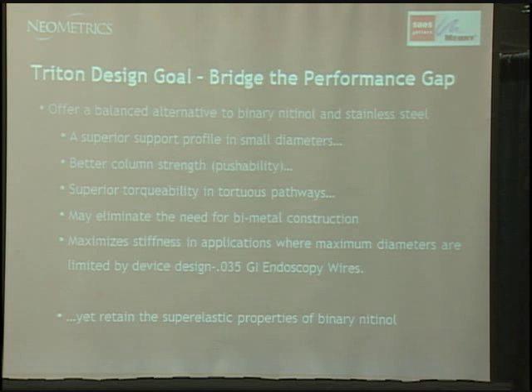So the solution to this performance gap between the two different materials is what we're calling the Triton Alloy. And the Triton Alloy is actually a modification of binary NiTi, which incorporates a cobalt component. And for those of you who are chemists, you may know that nickel and cobalt reside next to each other on the periodic table. And the interesting property that cobalt imparts to this material is it raises the peak loading forces, or the modulus, for lack of a better term, of this material, while retaining the superelastic properties of NiTi.